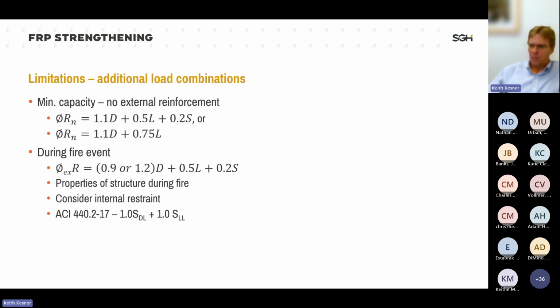A couple of things. One primary limitation when we're talking about FRP structures: when we're adding FRP, we have to have some minimum capacity without the FRP being present. That's shown in those two load combinations there. And why is this necessary? We think about FRP as basically an external reinforcement that's added onto a structure. That FRP can be damaged by impact. It can be damaged by people with grinders. It can be damaged by miscellaneous tradesmen that don't understand what it is. So there is a possibility, which may not be high, that an FRP can be cut or made useless during service. So we have this minimum capacity.